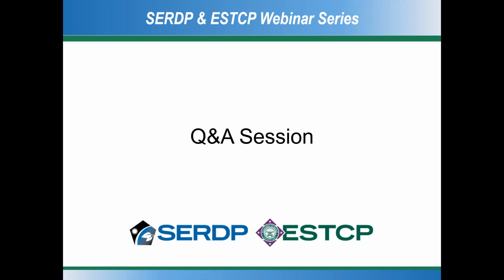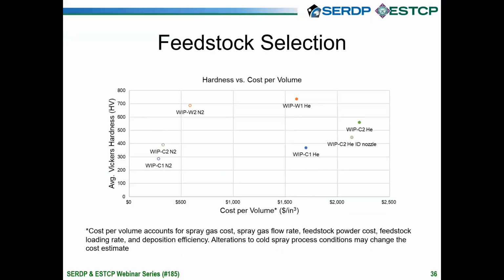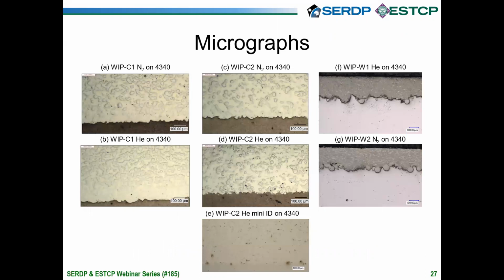The next question is about slide 27, where those images were shown. What are the spherical particles at the interface of the W1 and the W2 microstructures there? Yes, so for the WIP W1 and W2 coatings, actually for all the coatings, we use a bond layer. So the first layer of material is different from the subsequent layers of material. And the bond layer is a blended feedstock that's very similar to WIP C1 and WIP C2. So the bond layer is not an agglomerated feedstock, and that's why you see those spherical particles that are only at the interface. The purpose of that bond layer is to improve the adhesion strength of the material.